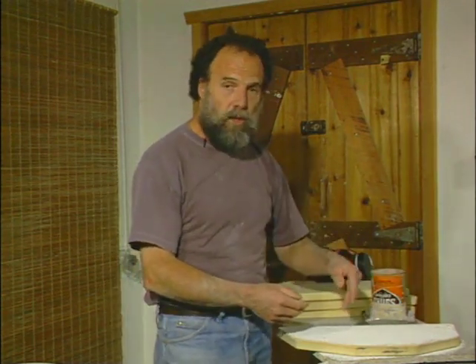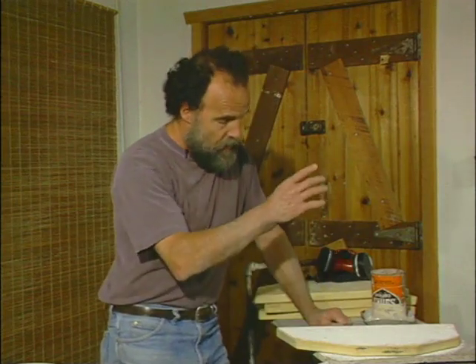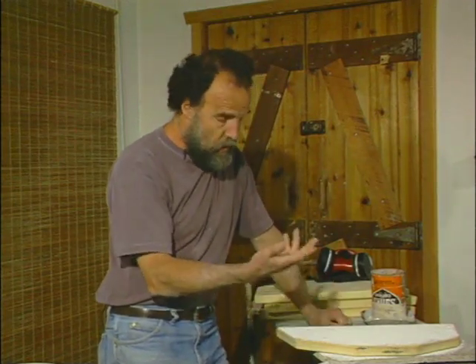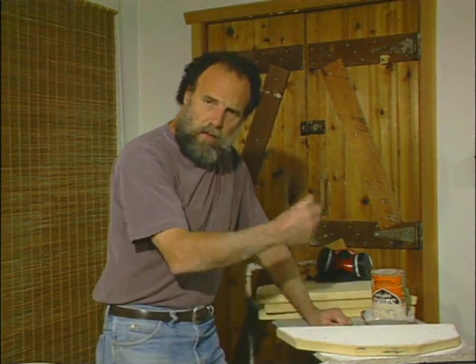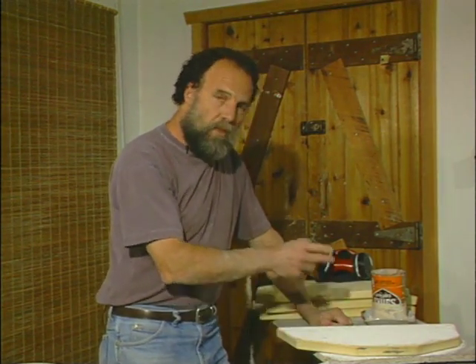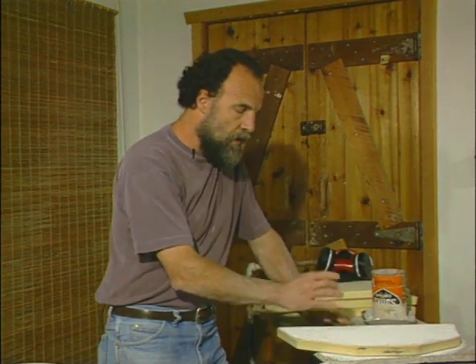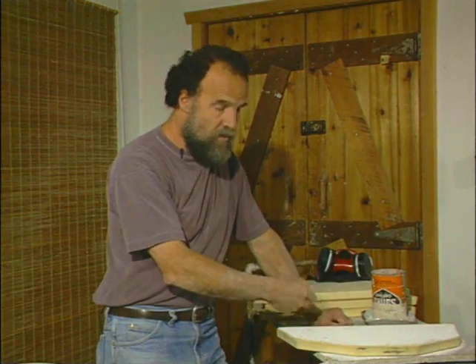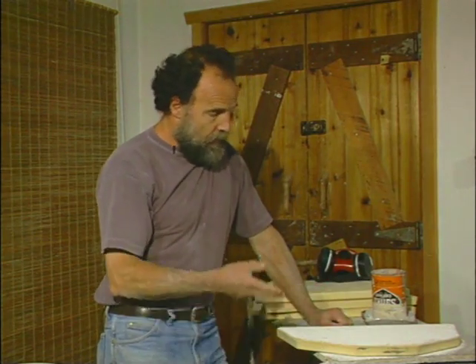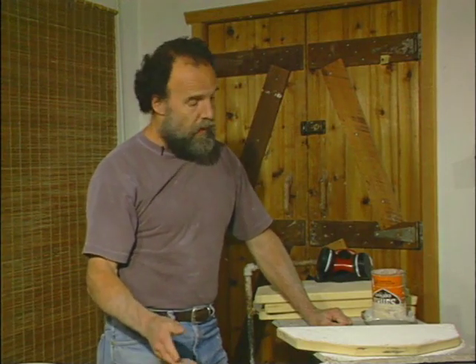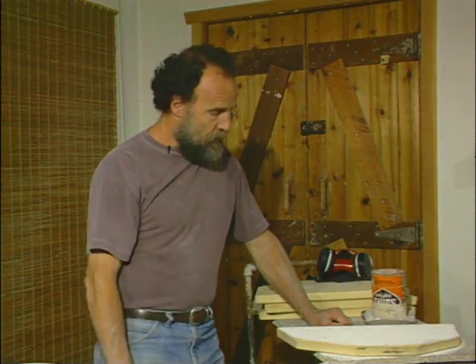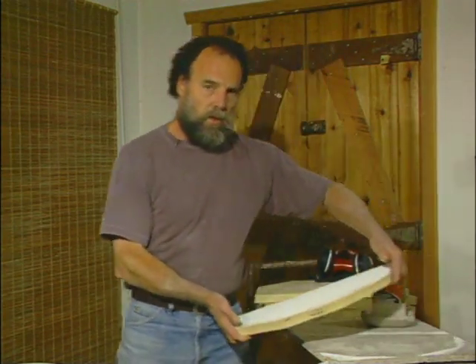The idea of coating the shelf with this silica flour is such that if there's any glaze on the bottom of the pot that you didn't wipe off prior to loading, or if any of the glazes run a little and run down onto the shelf, then the pot won't stick to the shelf. The run and the pot will come free of the shelf, and there won't be any marking and scarring on your shelf. Some potters choose to use a kiln wash made of 25% kaolin, 75% silica flour, mixed in the same way that we mix the slip when we're doing the decorating. And then that's just painted on with a paintbrush and allowed to dry, and it serves the same function. Okay, let's finish dusting down these shelves, and then we'll be ready to load the kiln.